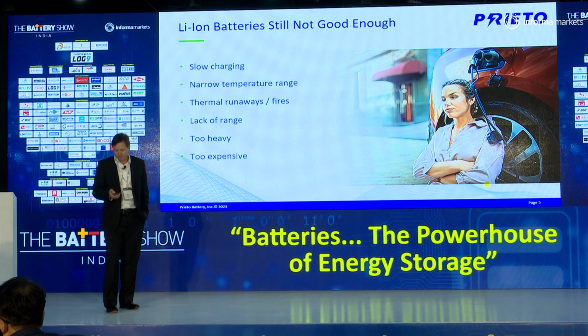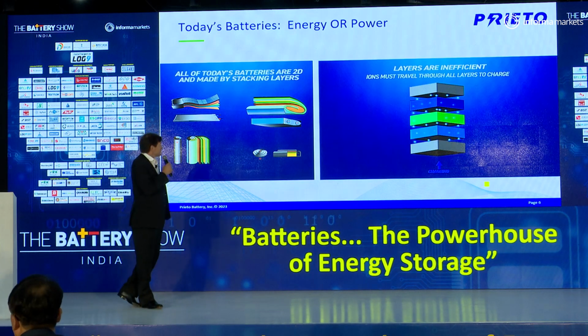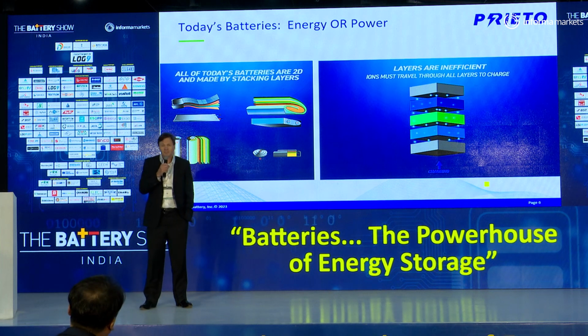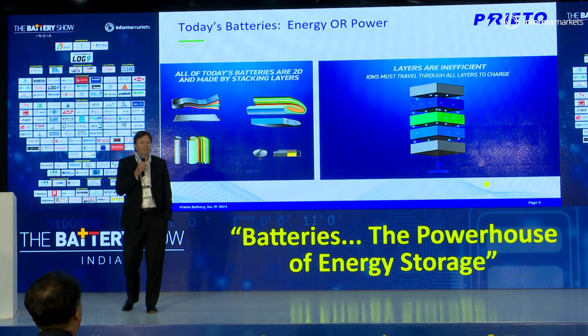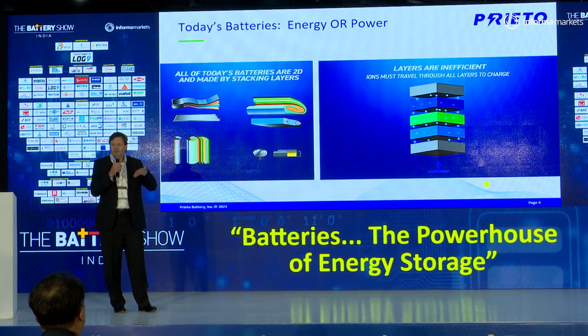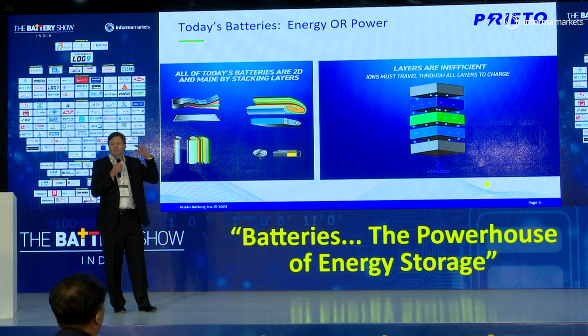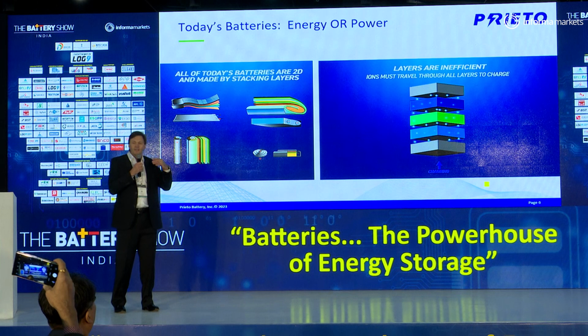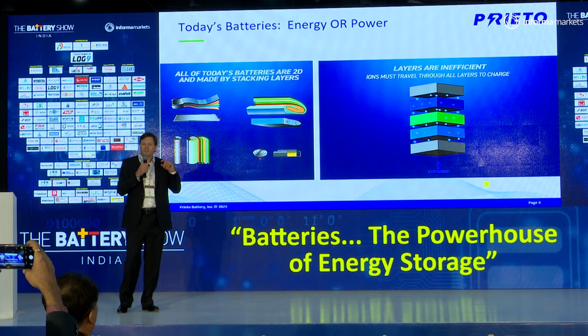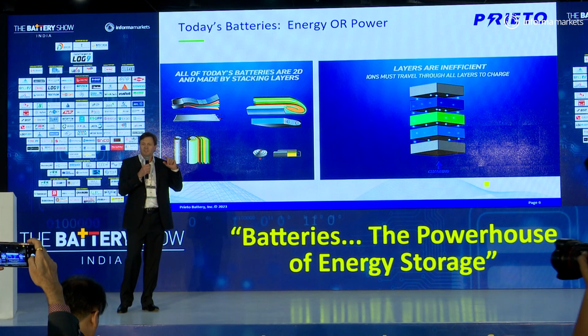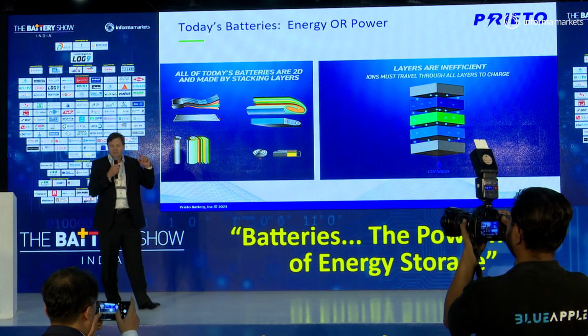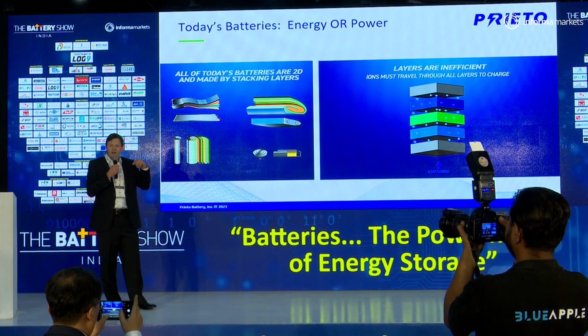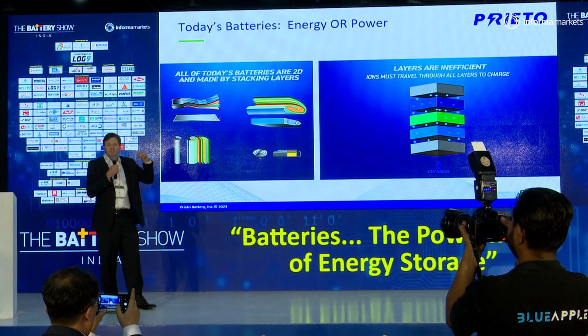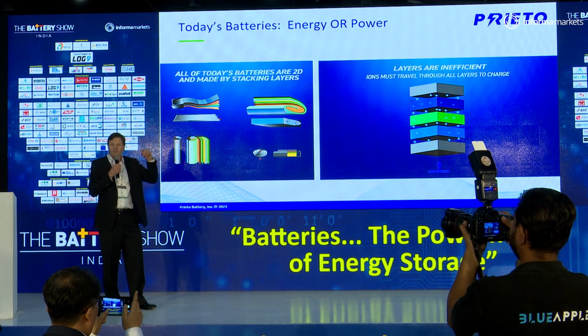We have that battery. If you look at today's batteries, they're 2D batteries. What we mean by that is it's a kind of layered pancake. You have a current collector, an anode, a separator, a cathode, and another current collector. If you want a high energy density battery, you have to put more energy into the anode and cathode, so you make those layers much thicker. And if you make those layers thicker, the lithium ion has to go from one side to the other. It's a much more arduous path, and it becomes very slow.